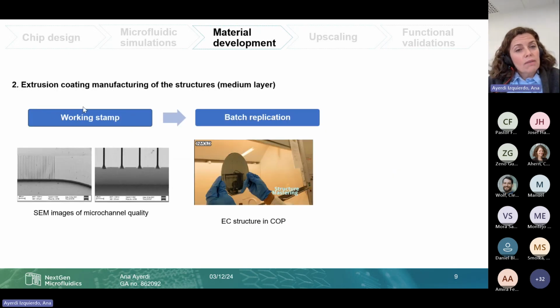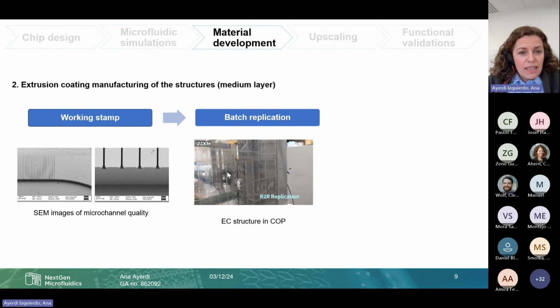For the extrusion coating manufacturing of these structures, the middle layer, a similar strategy was followed. On the left side of the slide, you can see the SEM micrograph as a quality control of the stamp that we were using for this replication strategy. And here we can also see a small video of how the batch replication process looks in real time.